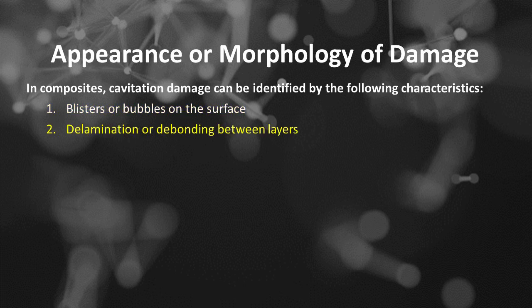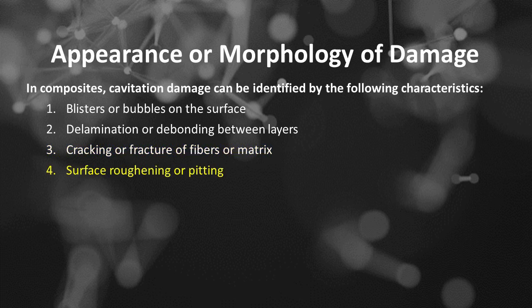Number 2 is delamination or debonding between layers. Number 3 is cracking or fracture of fibers or matrix. Number 4 is surface roughening or pitting. Number 5 is material loss or thinning.